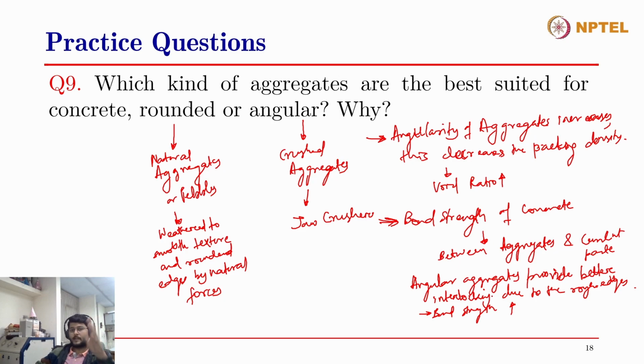So, in order to decide which is best suited for concrete, you have to find a good compromise between the angularity of aggregates in terms of decreasing the packing density, or the bond strength of concrete that you require for your concrete mix. Now, there is one fix to increase the packing density, as I mentioned. It is to introduce different sizes of particles, to use well graded aggregates, so that you have better packing and you also take advantage of interlocking between the angular aggregates.